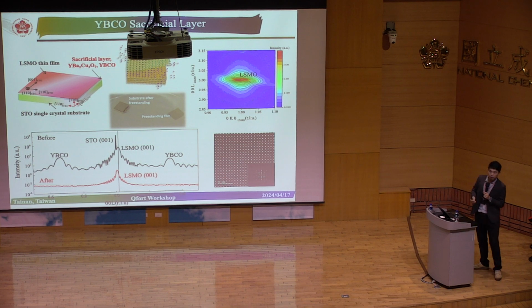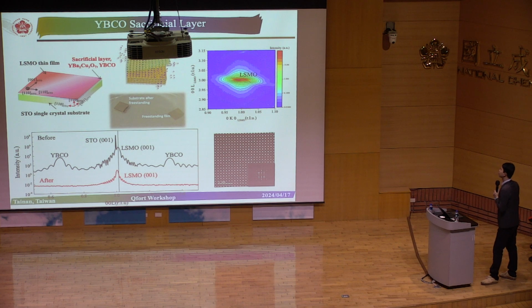Unfortunately, Paul Ju is not here. I hope that he wouldn't be mad at me simply because I used the classic YBCO as the sacrificial layer. But anyway, this is the classic X-ray diffraction that we can have. This is the as-grown sample just prepared, once we get it out from the chamber. We have a single crystal substrate, then the sacrificial layer, and then LSMO, which is the target material.